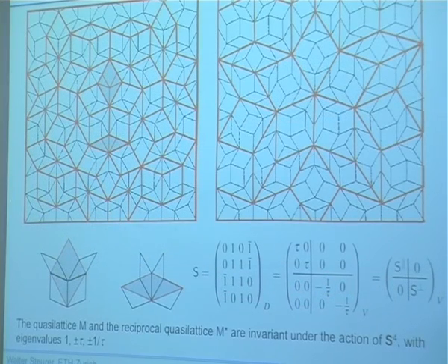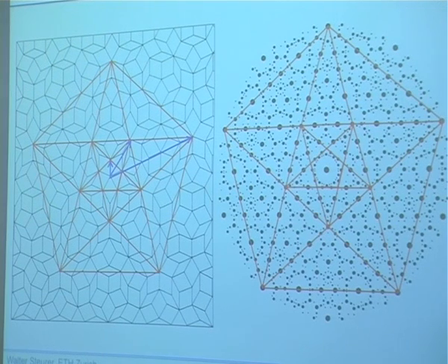Then one more property of a Penrose tiling is its scaling symmetry, as we have seen for the Fibonacci sequence. We have the possibility to scale it, and you have here in black a Penrose tiling, and then in red a scaled, inflated, enlarged other Penrose tiling superposed, and here you can also define a kind of substitution rule for this scaling rule, and you can scale it further. So this is a new kind of symmetry which acts on such a quasi-periodic structure. And this is another kind of symmetry: pentagrammal symmetry. So the old pentagram applies also to the symmetry of the Penrose tiling. And you see it's a kind of rotoscaling symmetry which applies to both the Penrose tiling and the Fourier spectrum of it.